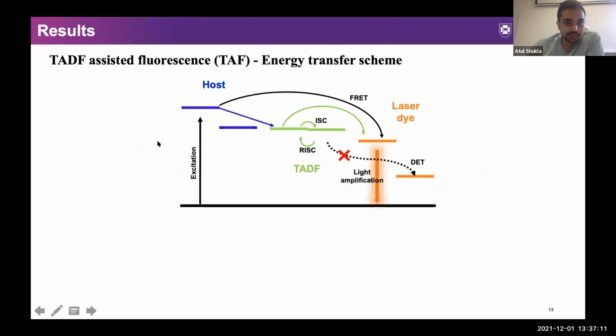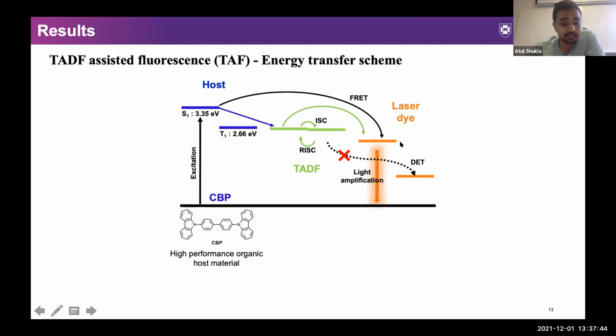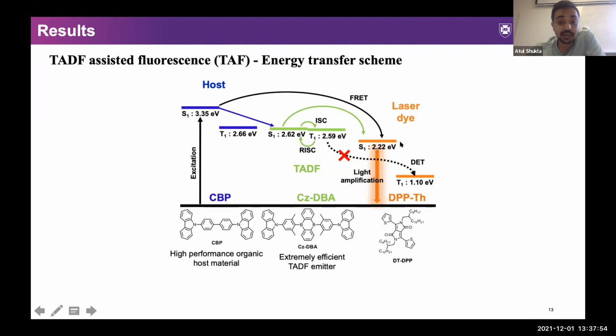Moving on to our approach, this is the energy level diagram, and we use a host matrix and a TADF assistant dopant, which recycles the triplet excitons, converts them into singlets, and then that singlet exciton can be transferred to the laser dye by Förster resonance. And we don't want triplet excitons to be transferred to our laser dye by Dexter energy transfer, as they would be lost if they move to the conventional laser dye. We used a high performance CBP as the main host material, CZDBA as our TADF dopant, and DPP as our laser dye for light amplification.